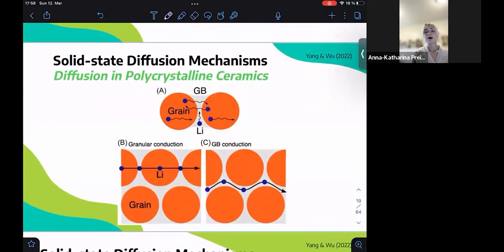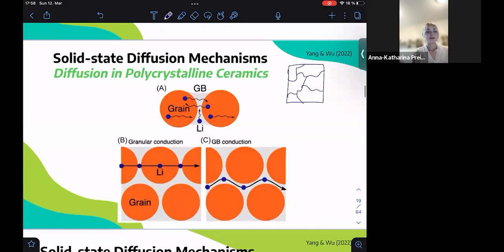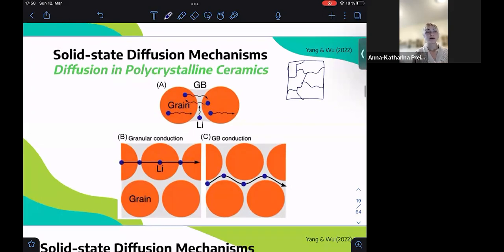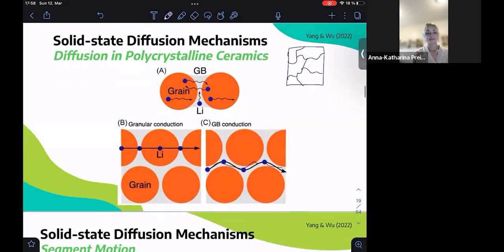And if we're talking about polycrystalline ceramics, which means that there are lots of different grains and thus grain boundaries making up the electrolyte, as compared to just one orientation of crystal, we also have different ways for the ions to move through it. And this really depends on the resistance of the grain versus the resistance of the grain boundaries. So often the ions will take a combination of different pathways, which include passing just in between the grains or passing through the grains.